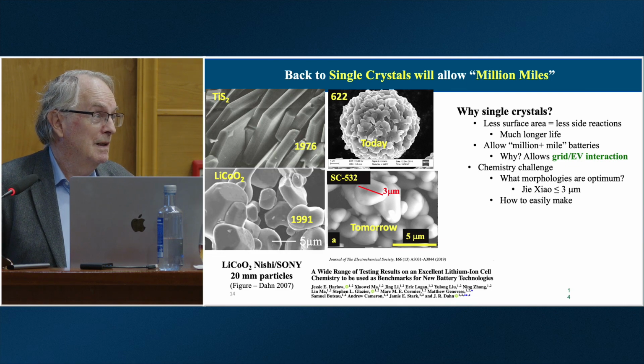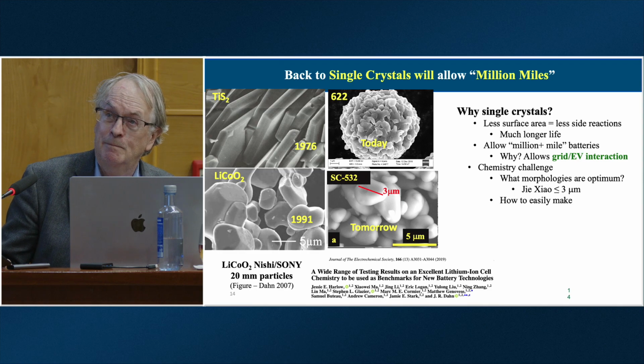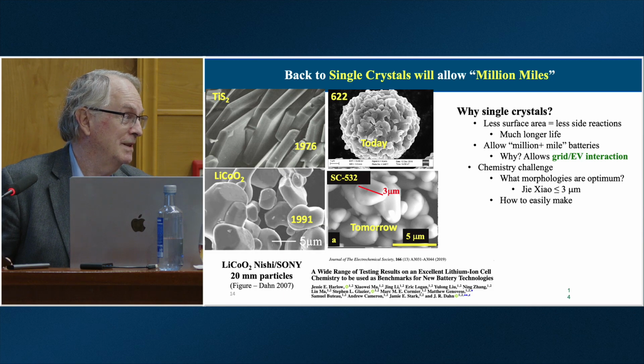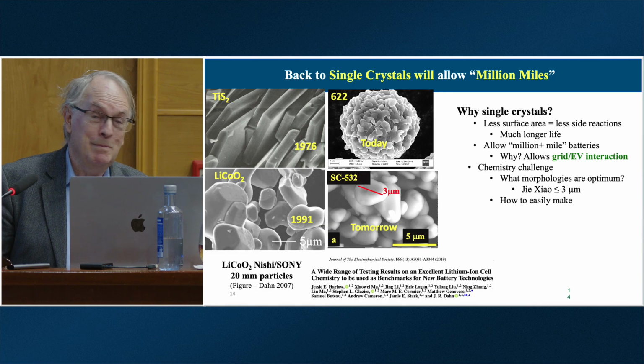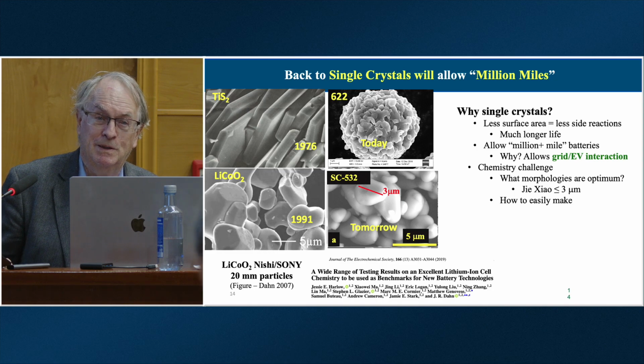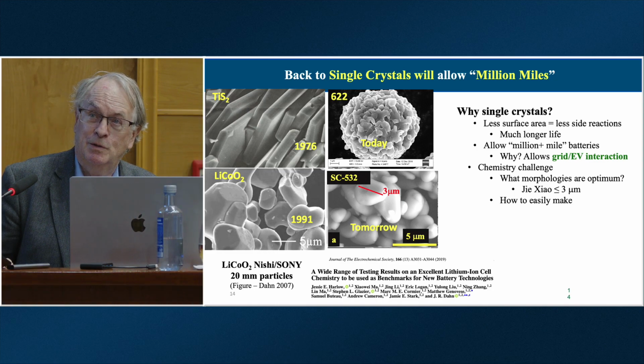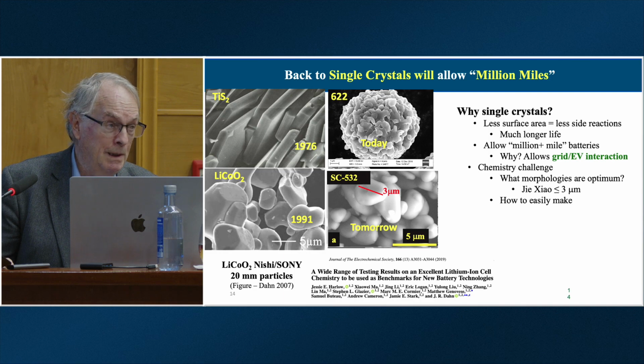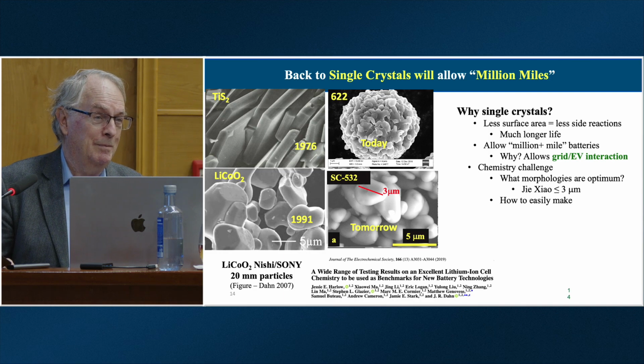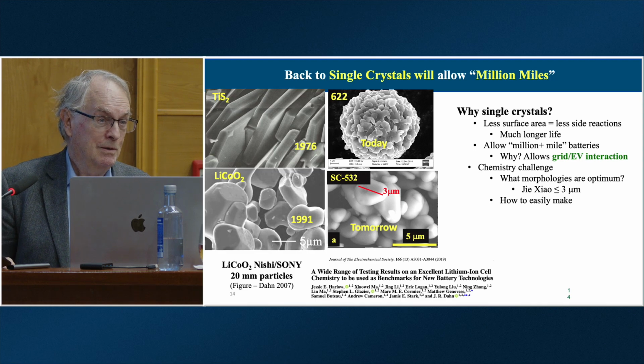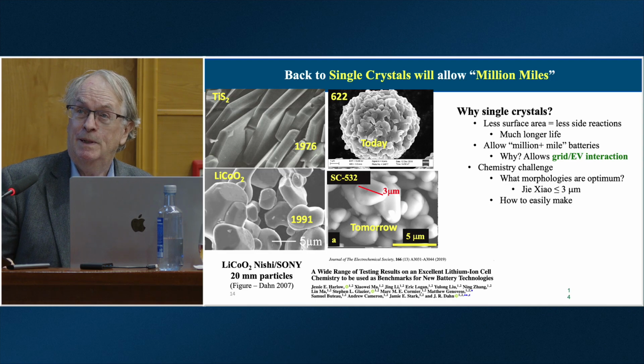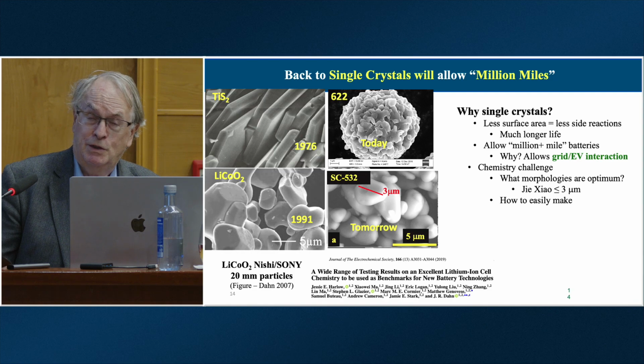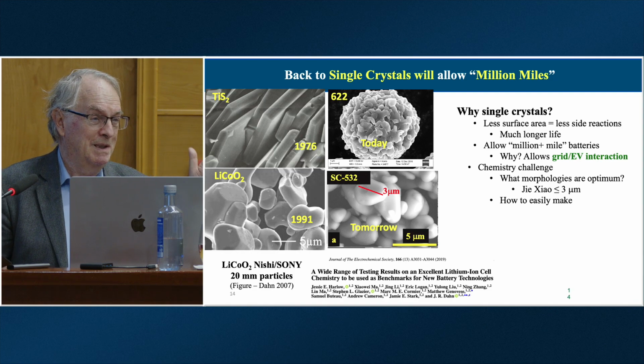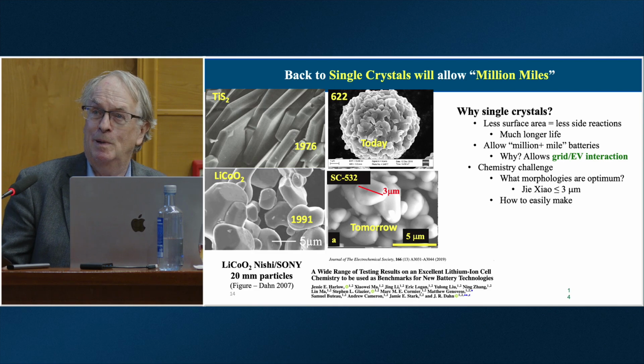So let's go back to where we started in the 1970s. Titanium disulfide, we used large single crystals. These were single crystals you could see with your eye. You didn't have to put them in the microscope, even though this is a microscopic picture. Some of these single crystals were several millimeters in size, and they reacted very well. Sony, when they built lithium cobalt oxide, wanted to make it as big as they could to increase the safety. But then when people wanted high rates, they went to these meatball morphologies, as I show you here for what we call 622. That just means 60% nickel, 20% manganese, 20% cobalt.